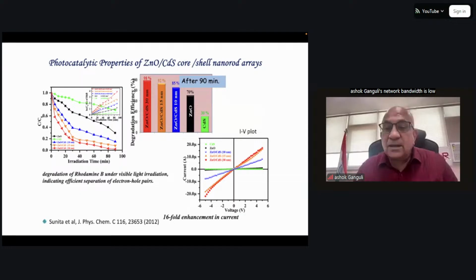And the same property, which is enhanced photocurrent, can also be seen in the enhanced reducing ability of this material, which is zinc oxide with cadmium sulfide, 30 nanometer shell. And you can study the degradation of a dye, and you see that the degradation is much faster for this heterostructure compared to pure cadmium sulfide or zinc oxide. Okay, so this is one example where you had two semiconductors configured in such a manner that their band edges are in a certain energy level diagram. They are following a particular pattern in energy.